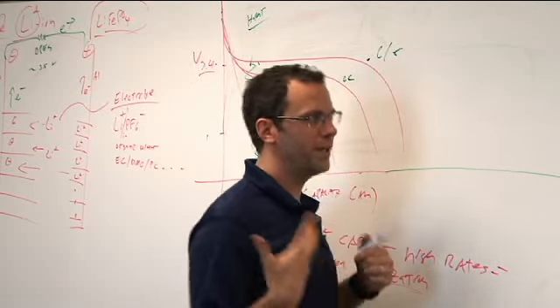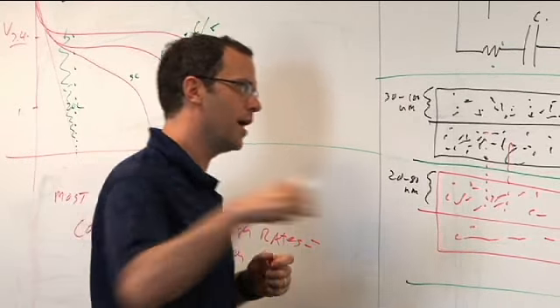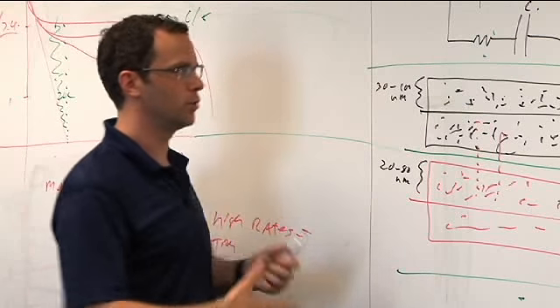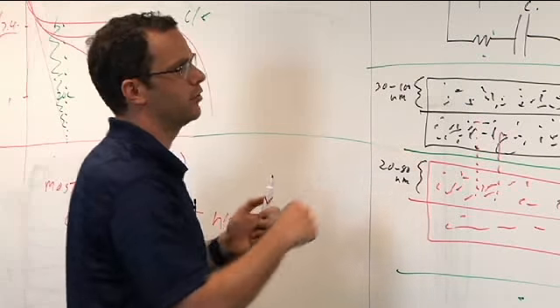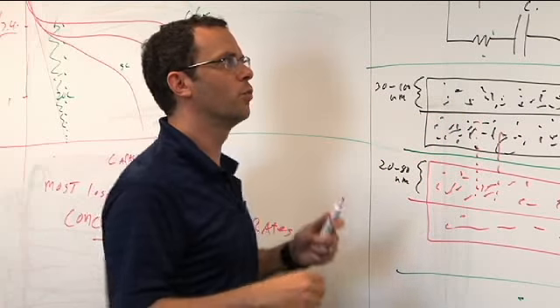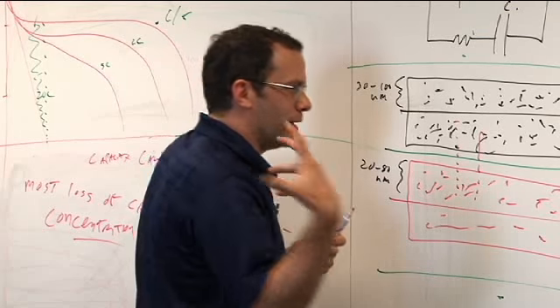And it's a combination of all these different things. There is one weakest link, and it doesn't really matter what it is, but because we are actually moving these physical ions through the structure, they are rate limited much more so than electrons, which can flow very freely through all my metal stuff and indeed through all of the conductive additive that we have in our electrodes as well. And so we have the situation where when we ask a lot, and this is where we have something